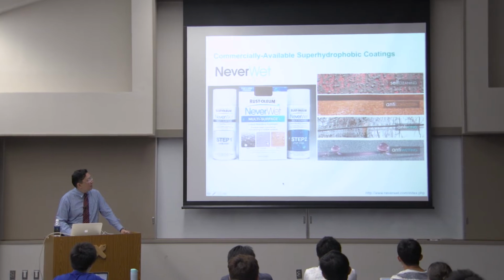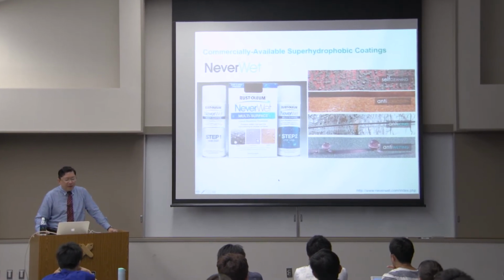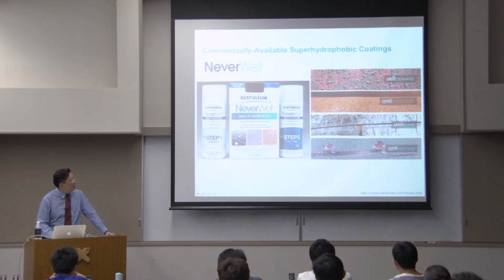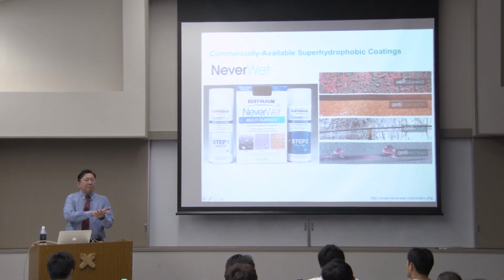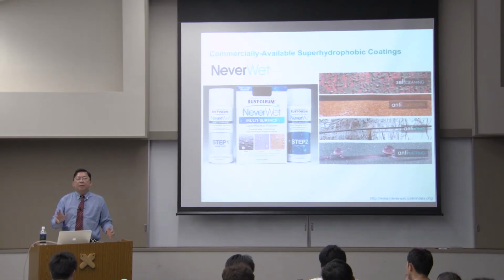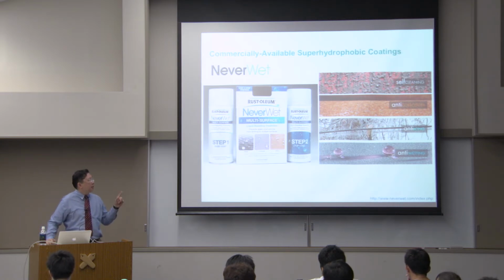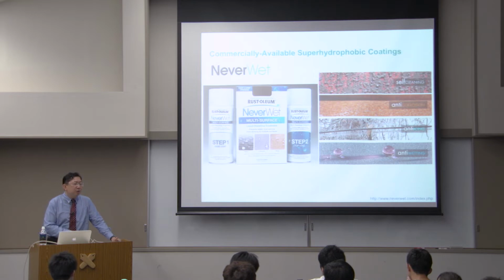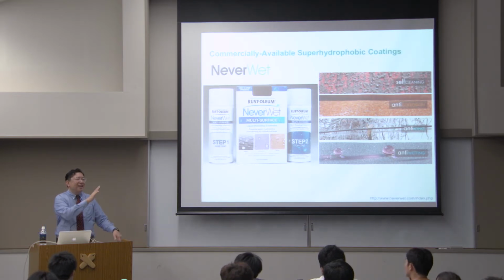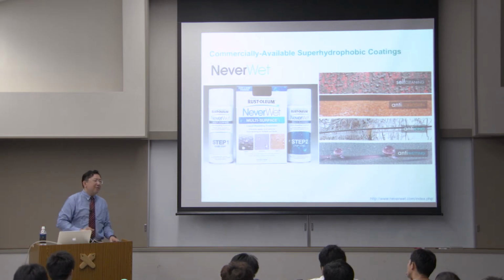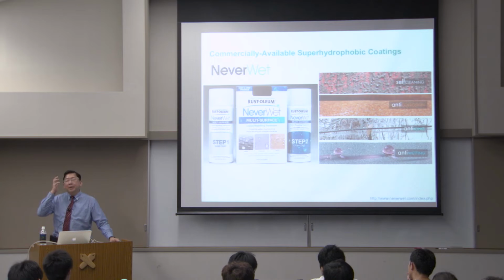This is a 2-step spray. The first spray prepares the base coat, or the material for the actual super hydrophobic effect, because this type of treatment can be used on many surfaces, from rubber shoes to clothes to your face—no, you don't want that—to any material. So you need to prepare a base coat, which is basically the primer.